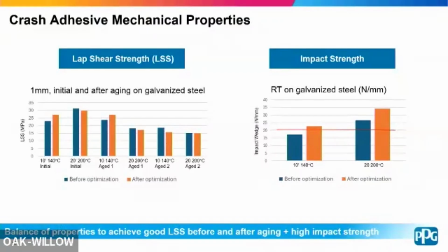So you can see in the blue, we had maybe not quite the lap shear strength that we wanted for that 140C cure. We were able to boost that up to above 25 MPa. After optimization, you get a little bit of a trade-off at the overbake condition, but still well within the range that would be acceptable, at least in the bounds of this particular request.